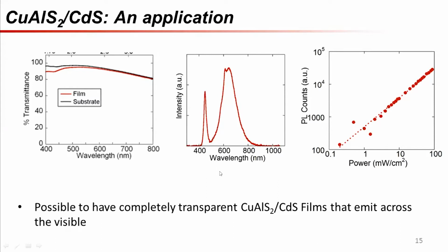The second issue, which is a more major issue, is the rock salt-like structure of lead sulfide, and copper aluminum sulfide is quite a bit different. It's a tetragonal chalcopyrite, and there are again massive differences in the softness of lead compared to aluminium. So all in all, it could be challenging. I'm not sure if you can replace cadmium sulfide with lead sulfide. It would be an interesting exercise if you can, certainly worth it, but I'm not sure if it can be done that readily. So it's not a question which I can answer because we have not tried it.